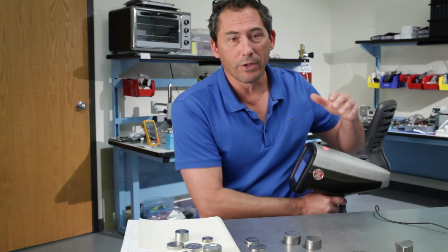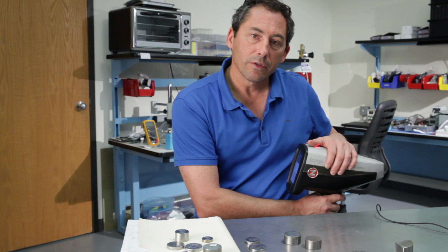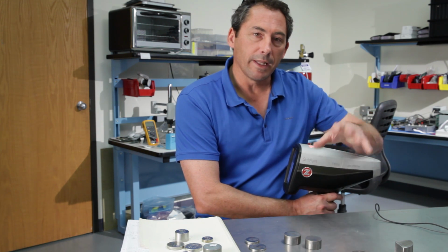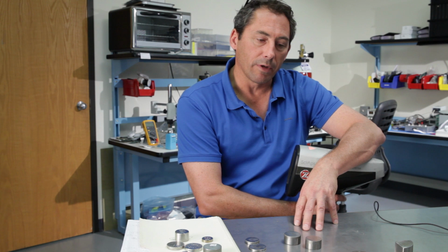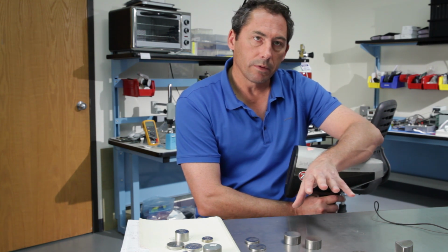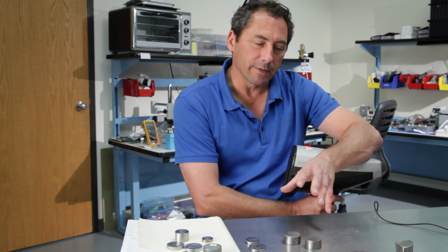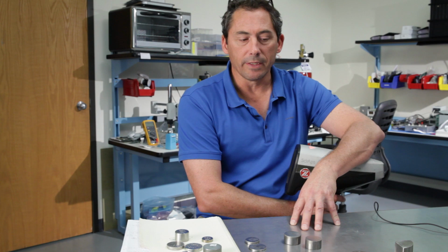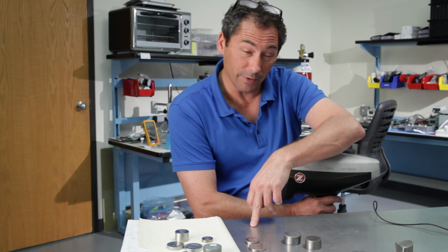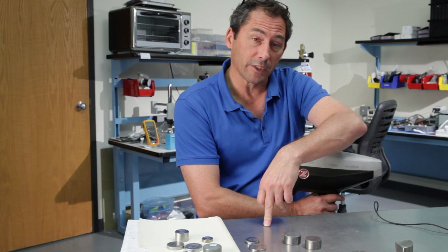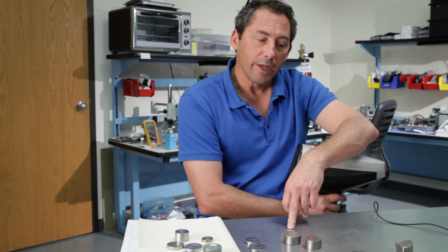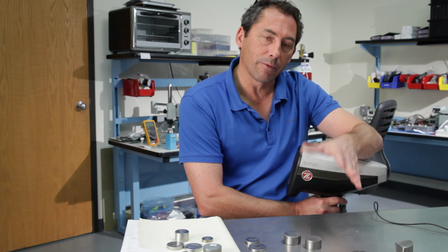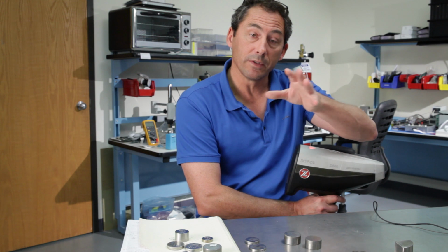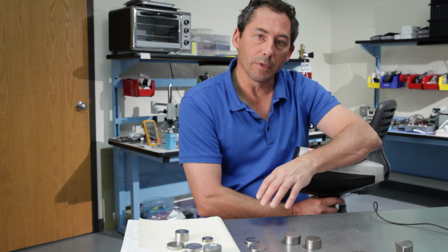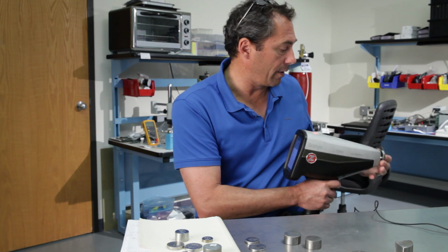Another thing I like to show, and this really goes out to a lot of the titanium sorting equipment that's used. Historically, a lot of Ti alloys have been sorted with arc-based spectrometry. And one of the well-known, not weaknesses, but well-known issues with that kind of sorting is the Ti 6242 and Ti 6246. They only differ by the 2% versus the 6% molybdenum in those two Ti alloys. And some of those arc-based sorting techniques can't separate 2% moly from 6% moly because in that technique the moly line saturates. But I just wanted to show that very quickly. So with LIBS, you don't have that problem. You can easily measure that moly.